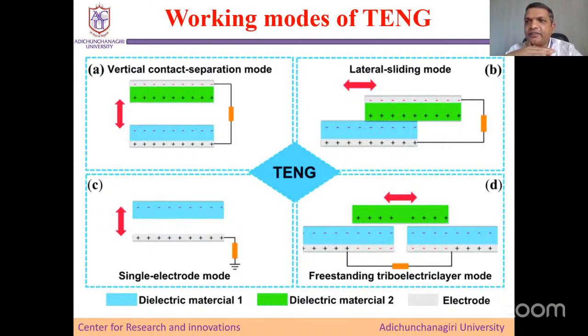And lateral sliding is a dielectric motion sliding laterally, producing alternating current. And single electrode mode uses a single dielectric material. In the case of freestanding triboelectricity, a free-moving dielectric alters the electrostatic balance between stationary electrodes, which are ideal for guided motion. Depending on the energy source, you can have vertical contact separation, lateral sliding, single electrode mode, or freestanding. So now we are focusing only on vertical contact separation because it's very easy to do.